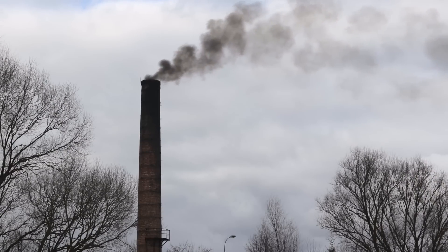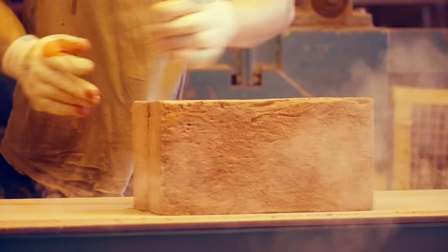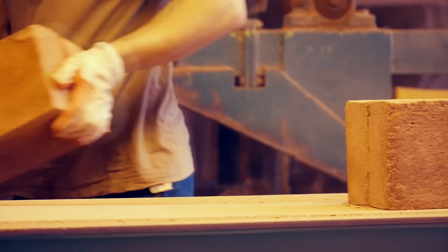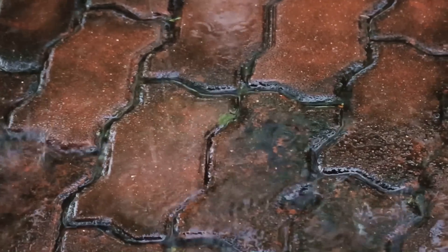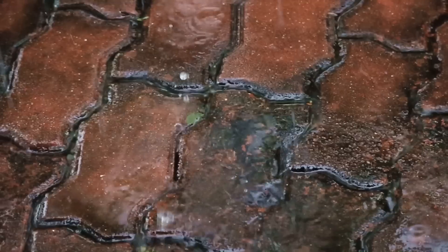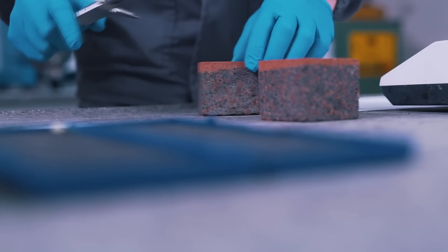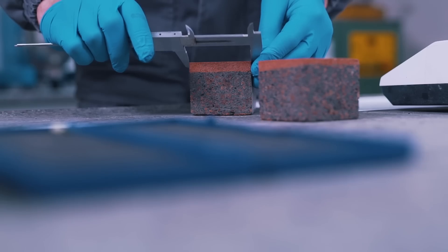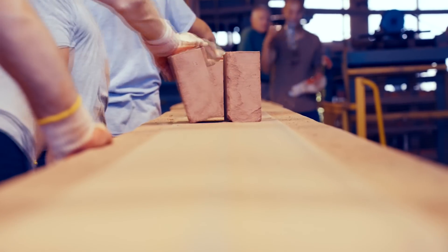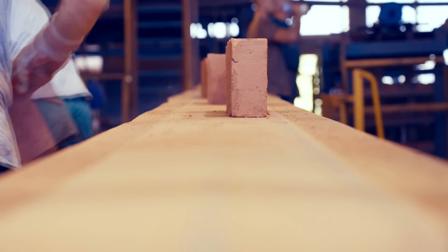After 36 hours in the kiln, a worker conducts a quality check. Weighing and measuring a sample ensures it meets design specifications. Bricks are designed to absorb some water, but not too much, as they need to interact with the wet mortar used by masons. To test absorbency, a worker breaks a brick in half and weighs it before and after soaking it for 24 hours. The weight comparison reveals how much water the brick has absorbed. Once the batch receives approval, the bricks are stacked and ready to go to the market.